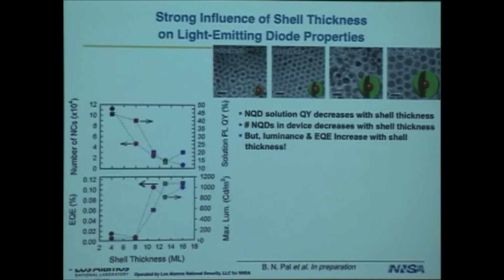If we look specifically at the effective shell thickness, we find something somewhat interesting. The dirty secret of giant quantum dots is that as you increase the shell thickness, the quantum yields actually go down. The best we've been able to achieve so far is about 50% ensemble quantum yield in solution for the very, very thick shell systems. That compares fairly poorly to the thinner shell systems that give us quantum yields of about 80%. So the solution phase ensemble properties are actually declining to some extent in the case of the thick shell systems.